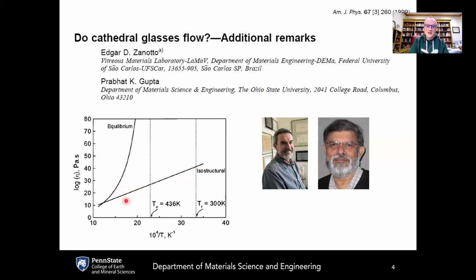But using this isostructural viscosity data for a modern soda-lime silicate glass, they came up with a new estimate for the time scale of glass flowing. And you can see that the new estimate was on the order of 10 to the 23 years. So many orders of magnitude faster than Professor Zanotto's previous estimate, but still much longer than the age of the universe itself. And so their conclusion remained the same, that the viscosity of glass at room temperature is much too high to actually observe flow on any realistic timescale. But this huge difference, this 9 to 10 orders of magnitude difference in the prediction between the old estimate and the new estimate shows the importance of accounting for the non-equilibrium character of the glassy state.